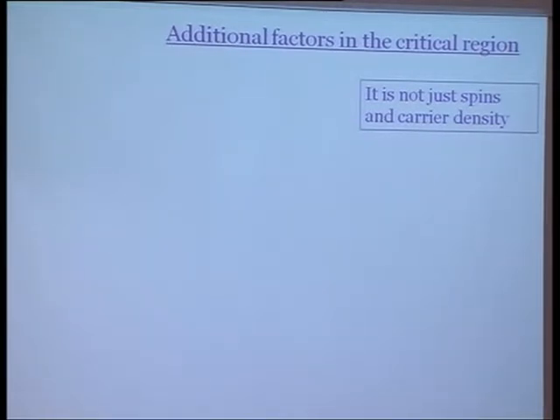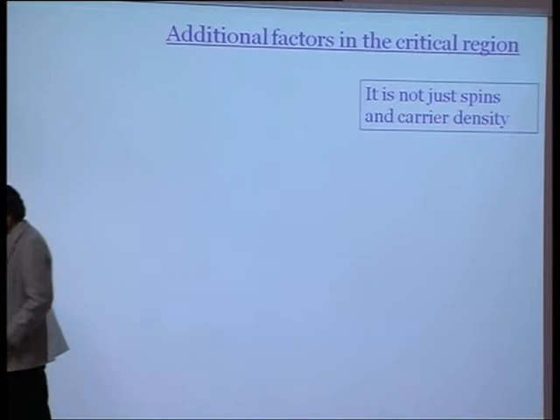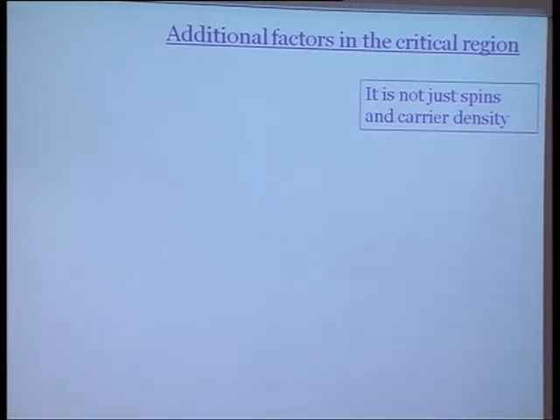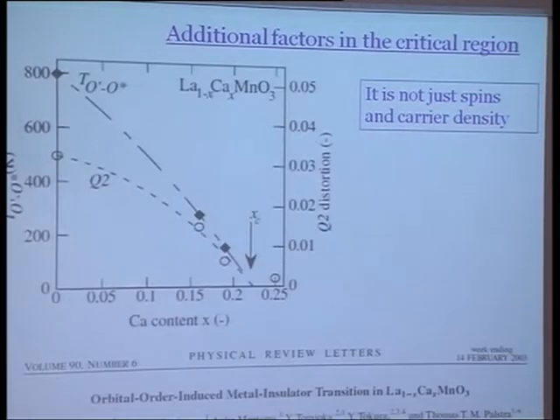Now, there are additional factors which come into the critical region. As I'm telling you, it is not only spins and carriers when you talk about the insulator-metal transition in this class of problem. There is something which happens to the orbitals and the Jahn-Teller distortion. This is an old neutron data, and it's very interesting data. It shows that very near the critical composition, how the orbital ordering temperature changes, and how the distortion, which is the Jahn-Teller distortion, varies.